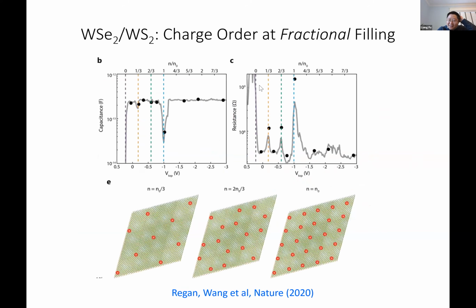Okay, so this is another experiment coming around the same time from the Berkeley group. And again, they used some kind of optical methods to detect the resistive states. And not only at half filling, when you have 1 hole per unit cell, there are correlated insulating states. But also you see that at fractional filling, when the number of holes is less than 1, when the filling is 1/3 or 2/3, these insulating states appear. So these are believed or proposed to be charge density waves.